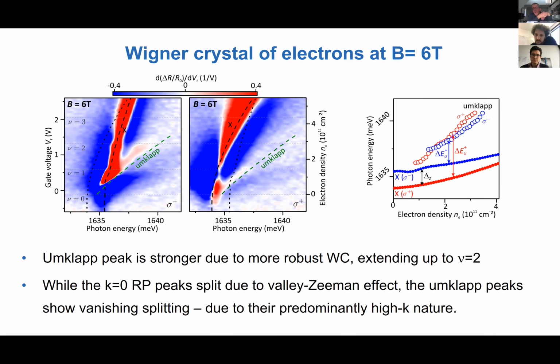I mean, more interesting possibilities could be that if our graphene contacts were closer, then the alignment of HBN and graphene could introduce a Moiré potential, which can then be sensed by excitons. Actually, Kim Fein-Mak and Jishan had an experiment like that, but in that case, I believe the graphene layer is only a nanometer or so away, whereas in our case, this is 70 nanometers. So in that sense, these length scales are completely inconsistent with any alignment or any angle, well, you don't need an angle actually because of the lattice mismatch. You will have a very short Moiré periodicity between HBN and TMD.